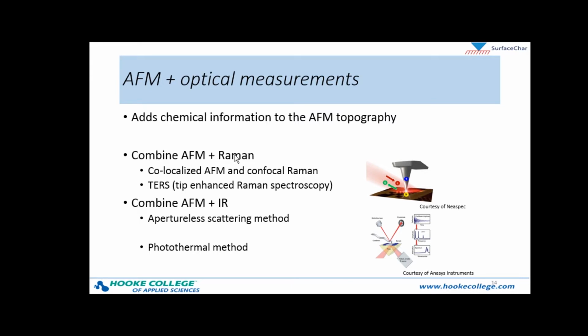AFM and Raman, the most popular way that that's being done right now, is doing these what are termed co-localized measurements of AFM and confocal Raman on the same area. And then for higher resolution, there's a technique called tip-enhanced Raman spectroscopy that's available. In order to combine AFM and infrared spectroscopy, there are also two main methods out there. One is an apertureless scattering method, a schematic of which is shown here, where you use the AFM tip as a very sharp antenna to really focus the IR light right underneath the probe. And then another method is a photothermal method that relies on some mechanical motion of the lever in response to some heating by the IR laser.